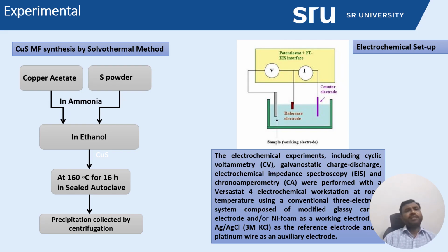So this reaction is a solvothermal reaction because we used only solvent. We did not use any water. Compared to the previous reaction, here we avoid the SiO2 template and change the solvent, using ethanol instead of water. The temperature also changes slightly: in the previous reaction we used 180, here 160.